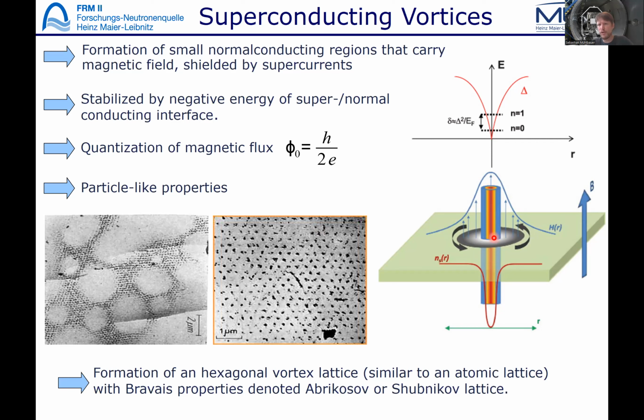We have the core of the vortex, which is normal conducting, and then we have the superconducting circular current, which shields the vortex. The fun thing with these vortices is that they are magnetic objects that arise on a completely homogeneous sample. But due to the quantization of the magnetic flux, they get particle-like properties. And of course, as particles arrange in a regular lattice, these vortices arrange in a so-called vortex lattice.